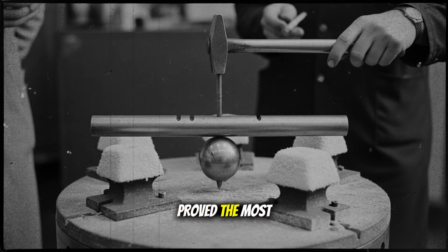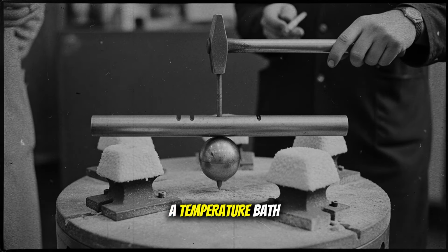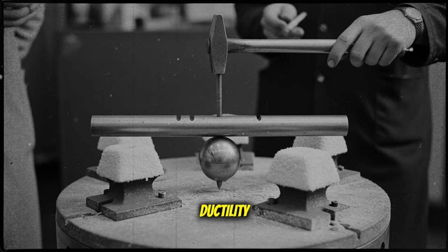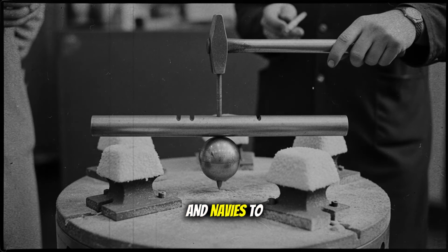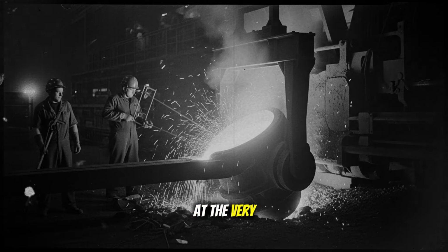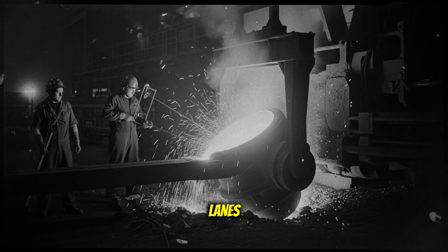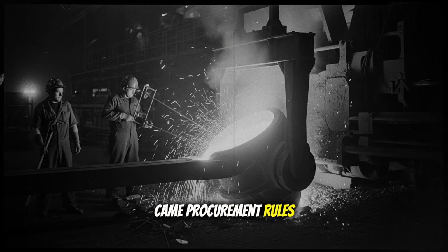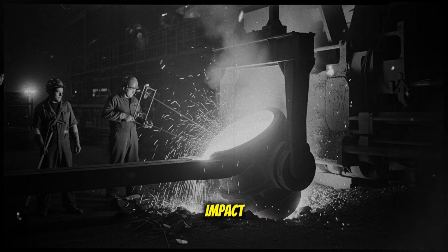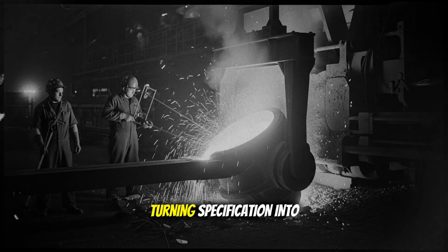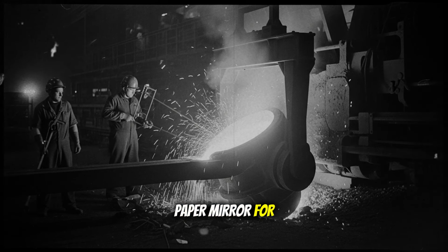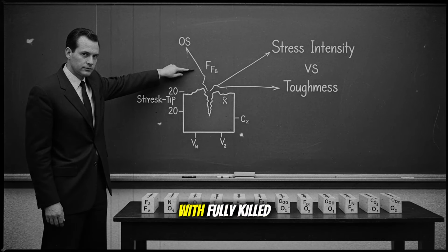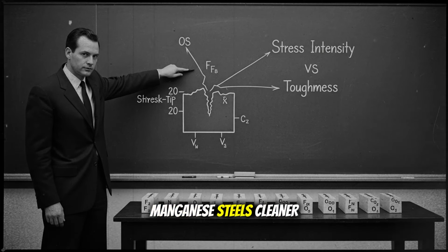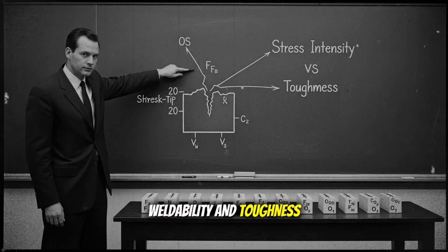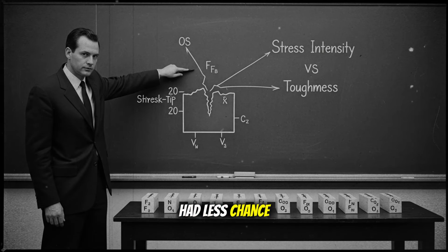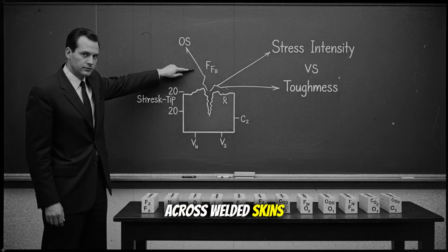The simplest tools proved the most powerful: a notched bar, a hammer, a temperature bath, and the Charpy curve that revealed where ductility fades into glassy fracture, allowing mills and navies to choose steels that keep absorbing energy at the very temperatures that once wrote Liberty tragedies in winter lanes. From those curves came procurement rules and class requirements that tied acceptance to low-temperature impact performance rather than to ambient strength alone, turning specification into prevention instead of a paper mirror for good intentions. The mills responded with fully killed, fine-grained carbon-manganese steels, cleaner, better balanced for weldability and toughness, so a deck corner in January had less chance of birthing the bright line that once sprinted across welded skins.